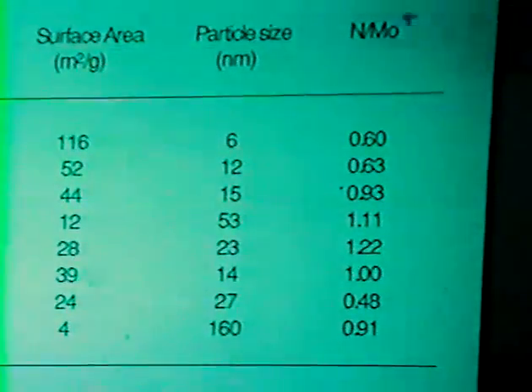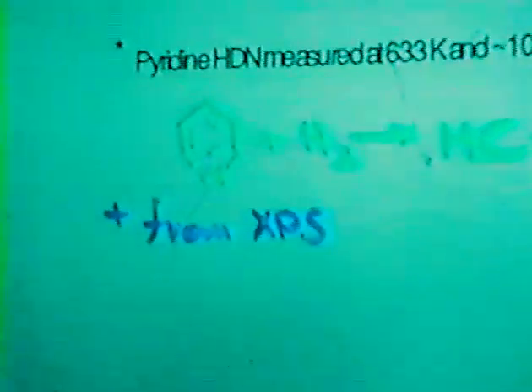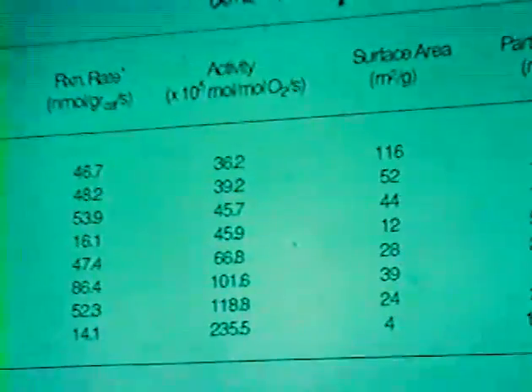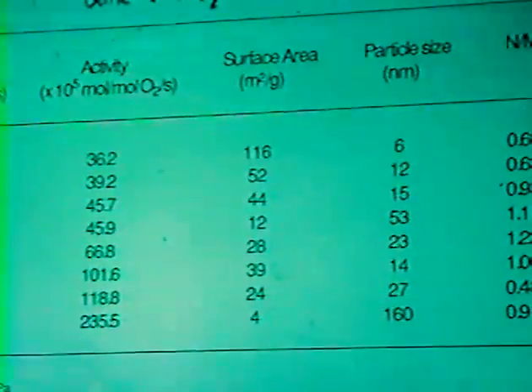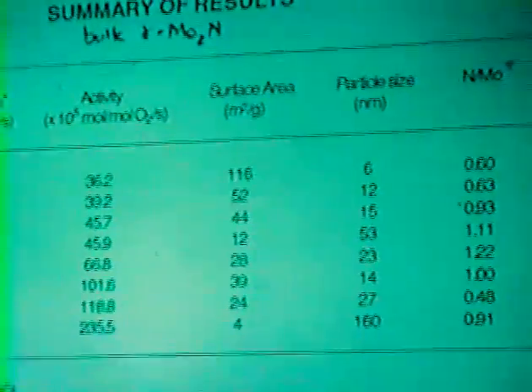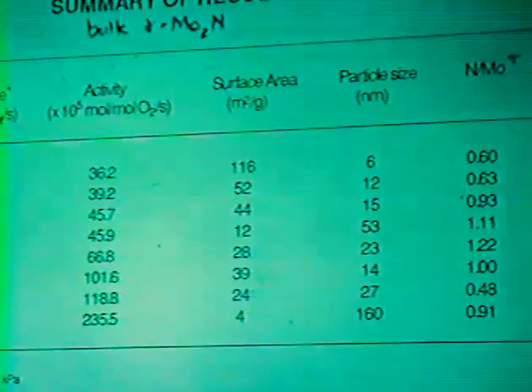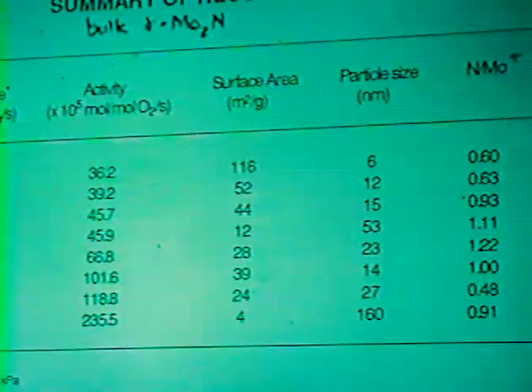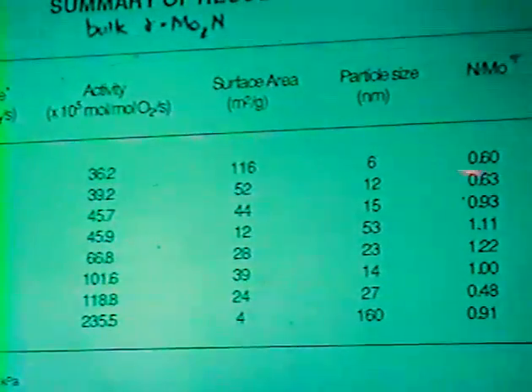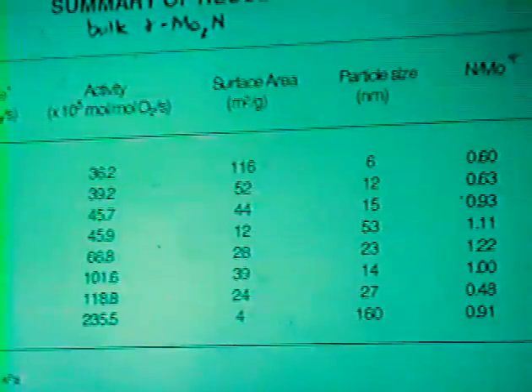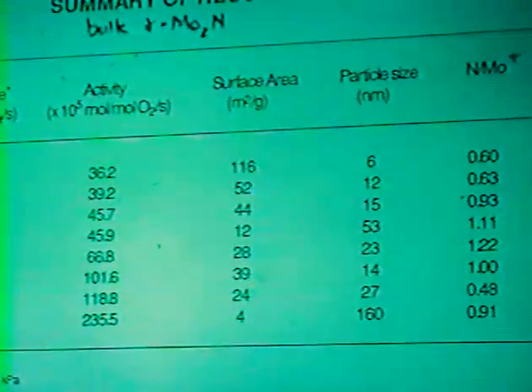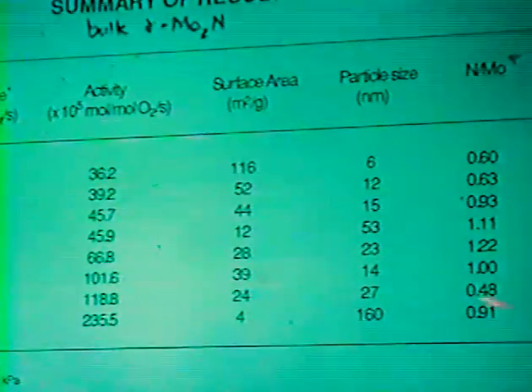I've listed the results in order of activity here based on oxygen uptake, starting with sample number 2, which has the lowest activity, going to sample number 8, which has the highest activity. You'll remember that number 2 is the highest surface area material, while sample number 8 is the lowest surface area material. Convert those surface areas into particle sizes, and we find that there is more or less a monotonic increase in the activity with an increase in the particle size. As we increase the particle size, you can see more or less that the activity increases. And this is a somewhat significant increase in activity, certainly outside of the experimental error that's expected for the reaction rate measurements or the particle size measurements.